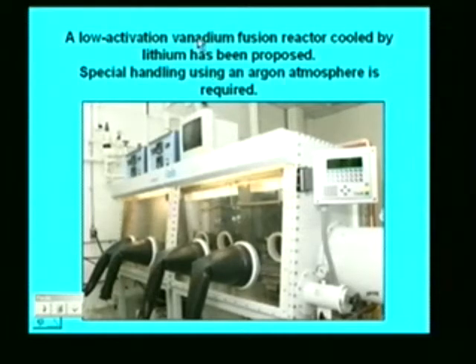But if you're going to use lithium, special handling is required, particularly a very high purity argon atmosphere. So the work with lithium is done in a high purity argon glove box. And in this glove box, we keep oxygen, moisture, and nitrogen below 1 ppm.